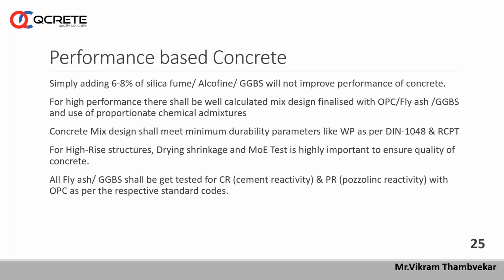If we are using very good material and a proper mix design, see, we have produced up to M50, M55 grade of concrete without using any supplementary cementitious product such as silica fume. Only fly ash we have used in a certain percentage to get good workability and good paste to have a good finish and good strength also.